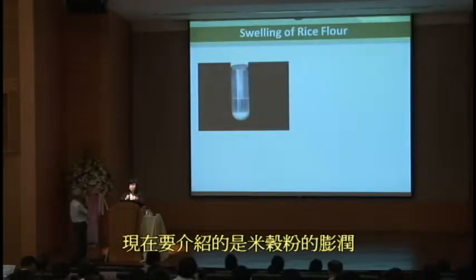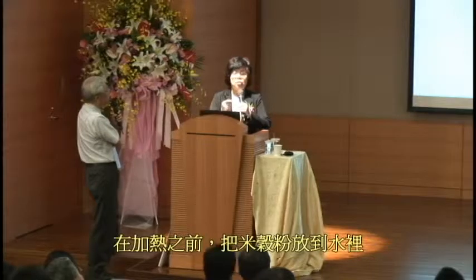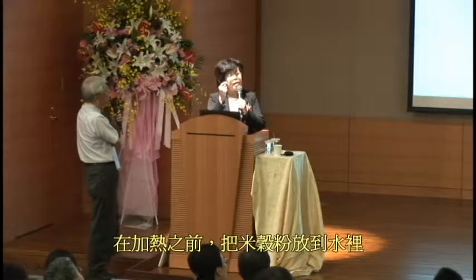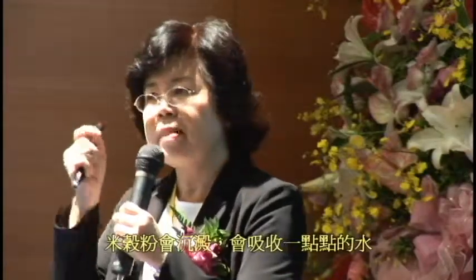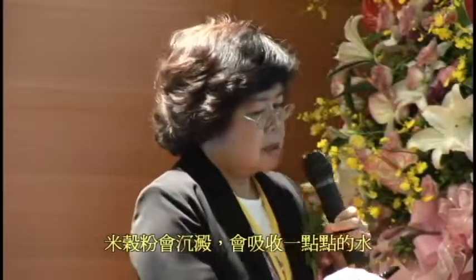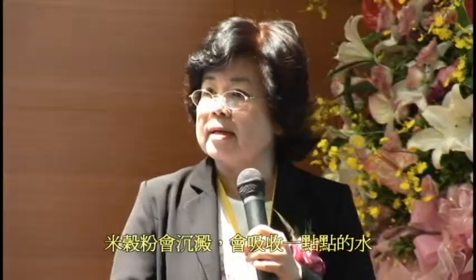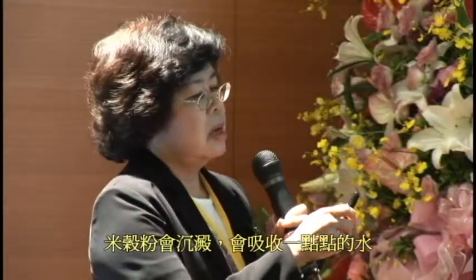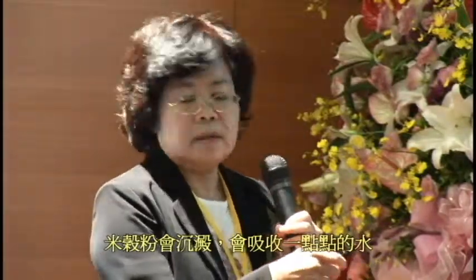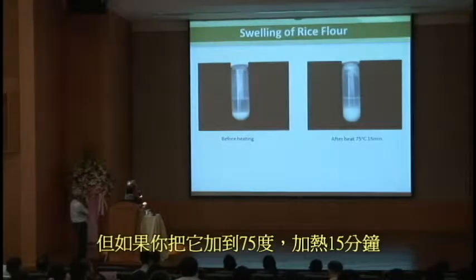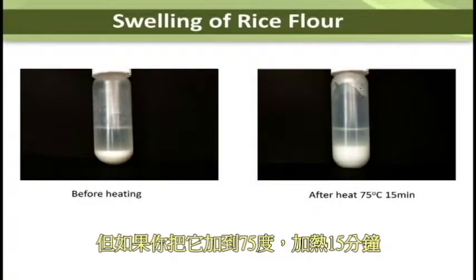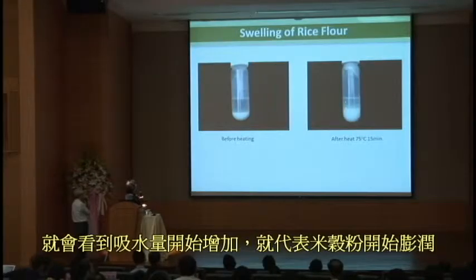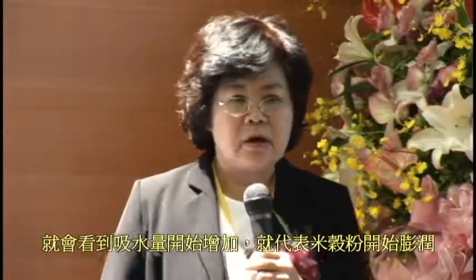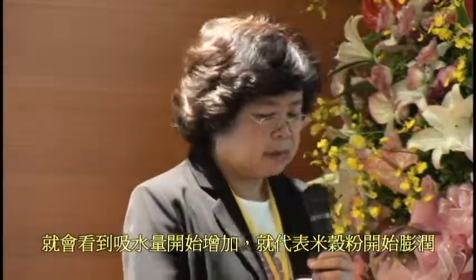As you know, when you put rice flour in cold water, it absorbs a little bit and swells a little bit, not much. So this one is before heating the rice flour and water. But after heating at 75 degrees Celsius for only 15 minutes, you can see that the rice flour swells. Now look at the effect of storage on the swelling value of the rice flour.